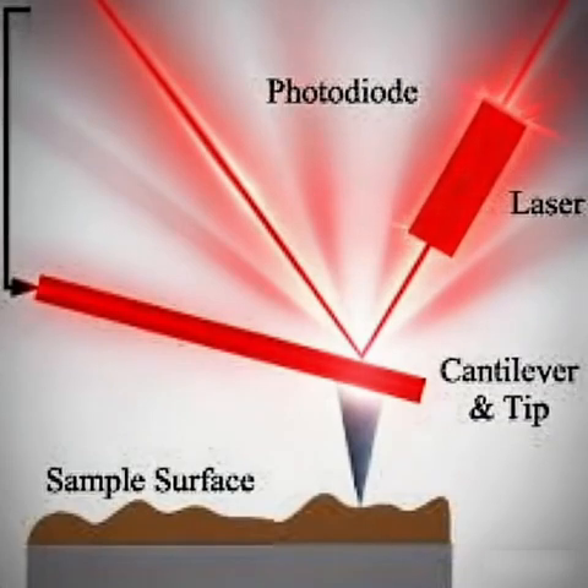Wow, the wires themselves rearranging. How does AFM catch that? Well, AFM methods are invaluable here too. See, AFM can measure the local resistance along those metal lines. It can detect tiny fractures or voids before they become complete breaks, early warning. And just general morphology scans, looking at the surface shape with AFM, can detect those surface changes, finding the hillocks or cracks very early on, often before there are any electrical symptoms you could measure otherwise.